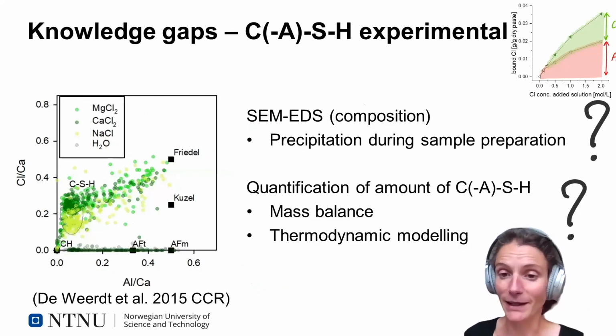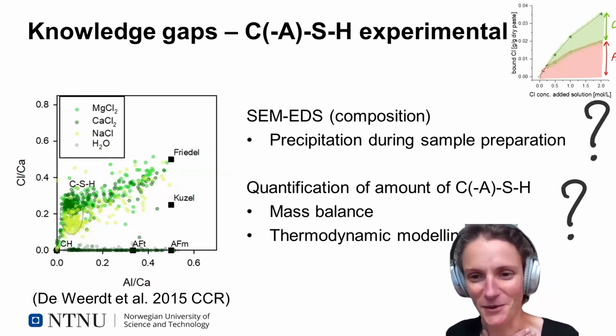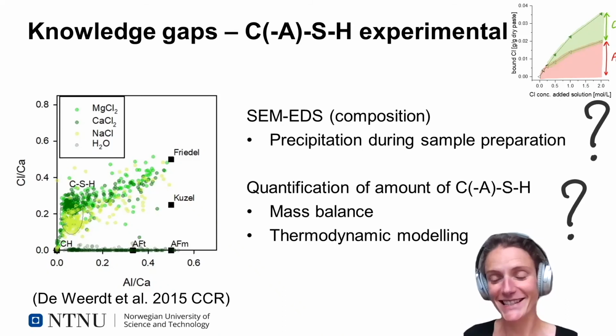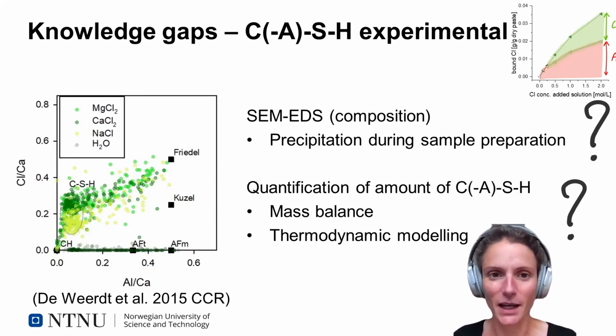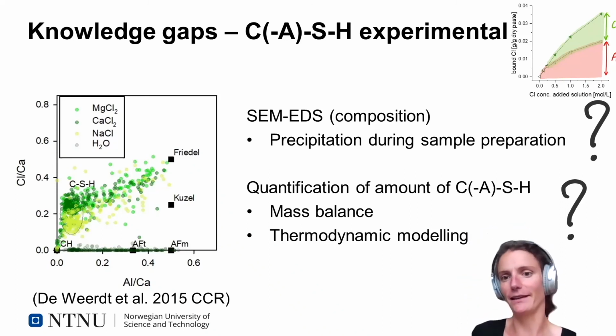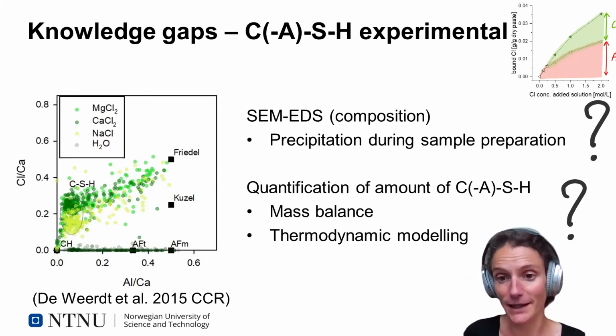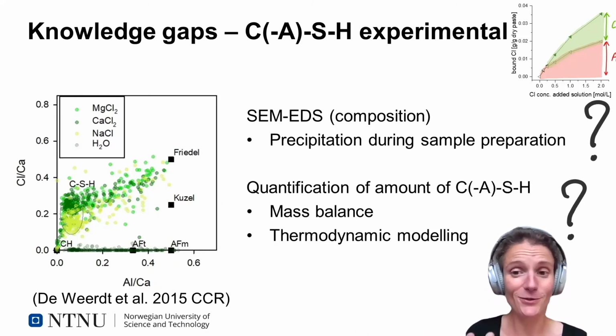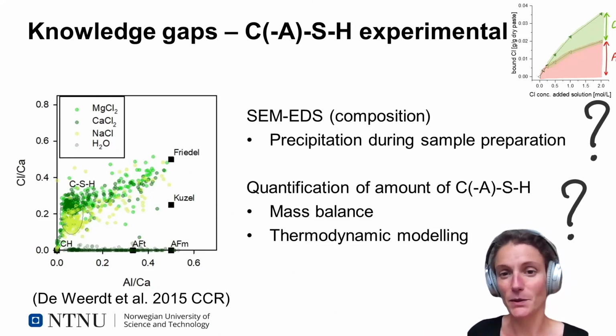Then on the experimental side, a little bit more what I work with, CSH is also very challenging. We can determine its composition in a cement paste using, for example, SEM-EDS, though there are challenges in sample preparation. And we not only need the composition, we also need the amount to be able to say how it contributes to chloride binding. And there's also quite some challenges to determine the amount of CSH in the system.